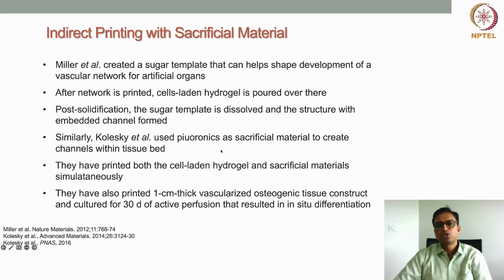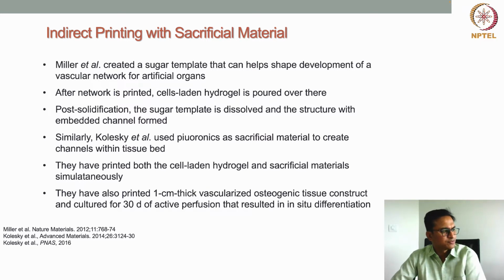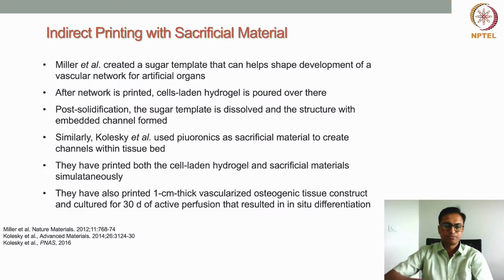So they have used Pluronics as a sacrificial material to create the channels within the tissue bed. Pluronics is a material which, above 20 degrees centigrade, is a gel-like material, but below 20 degrees it is a liquid material. So what they have done is use Pluronics to print the channels that can be sacrificial materials, but simultaneously